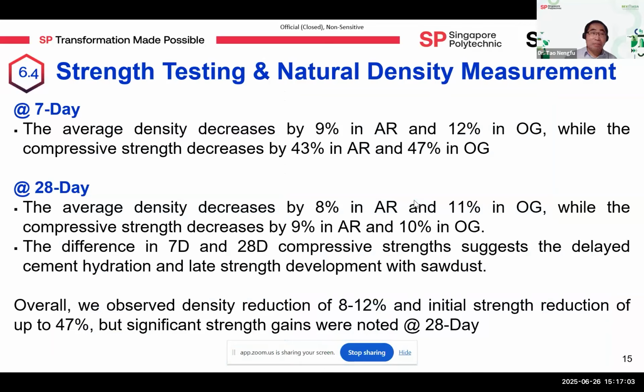From the bar charts on the previous slide, we can take a few key points. At 7 days, the average density decreased by 9% in AR and 12% in OG, while the compressive strength decreased by 43% in AR and 47% in OG. At 28 days, the average density decreased by 8% in AR and 11% in OG, while the compressive strength decreased by 9% in AR and 10% in OG. The difference between 7-day and 28-day compressive strengths suggests delayed cement hydration and late strength development with sawdust. Overall, we observe density reduction of 8 to 12% and initial strength reduction of up to 47%, but significant strength gains were observed at 28 days.